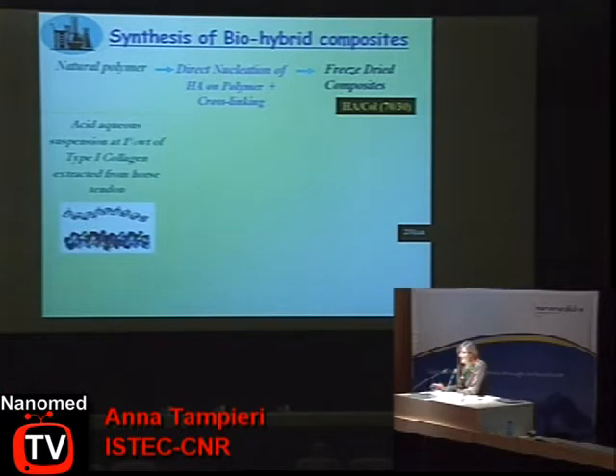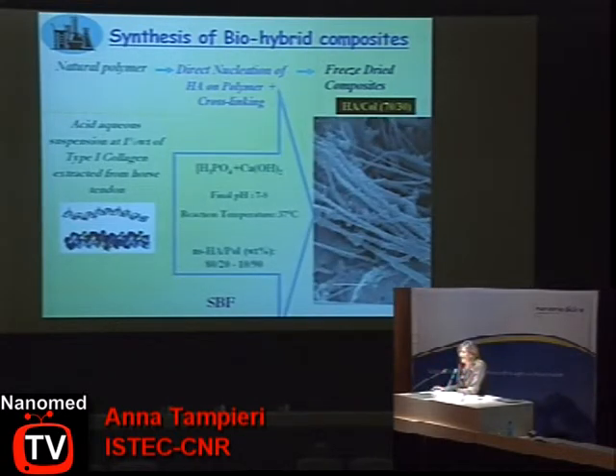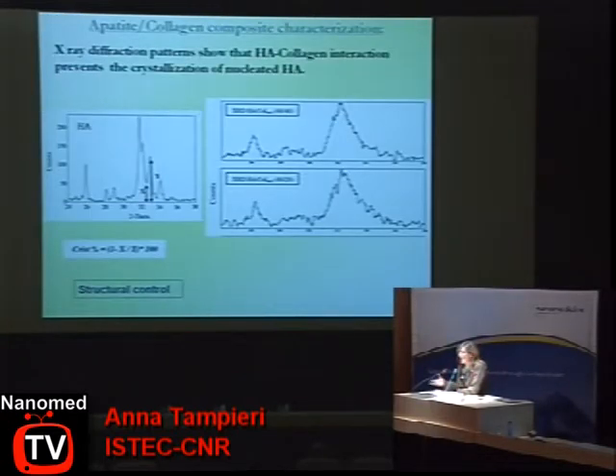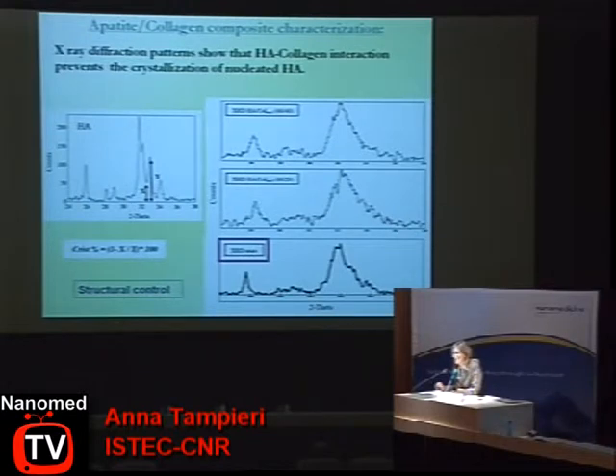So we tried to reproduce this process, exploiting the self-assembling ability of collagen fibers as a function of pH variation, and to induce simultaneous nucleation of the mineral phase in physiological condition, starting from collagen type 1 extracted from horse tendon, inducing the nucleation of the apatitic mineral phase. What we obtain is a mineral phase, as you can see on your right, which is very similar to the mineral phase of natural bone.